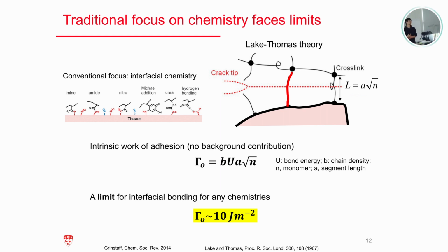For the first contribution, gamma 0, essentially you need to break the bonds on the surface. Those are the existing toolbox, right? Chemists have been very creative in creating different kinds of chemistry to form carbon-nitrogen bonds or a variety of other chemical bonds on the tissue surface. However, when it comes to the energy consumed, we use the pretty well-established Lake-Thomas model in polymer physics to calculate the amount of energy needed to break or cleave the bonded polymer chain.